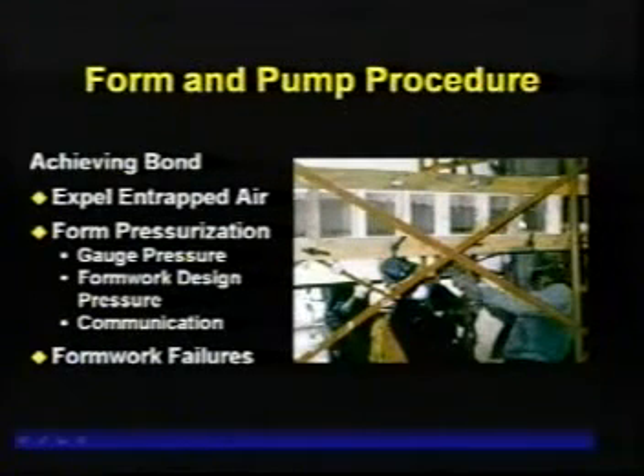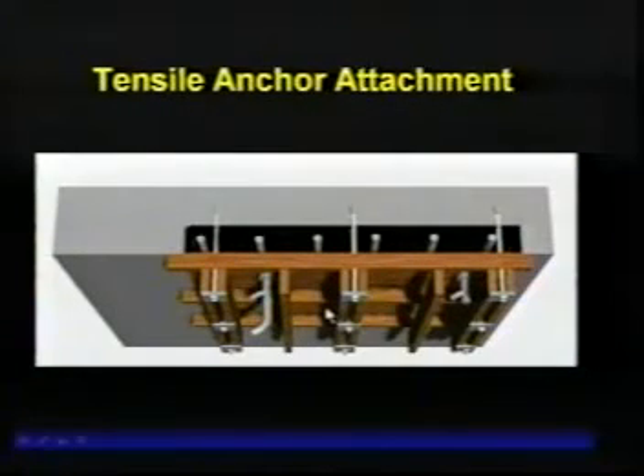And this is the last in the sequence, showing that the cavity has been filled, the form is pressurized, and there's actually some pressure gauges you can see right here, and we actually pressurize it to about 14 psi, at which point the valves are turned off. You can see how this consolidates it by just the internal pressure, how it pushes it around and consolidates, and especially the intimate contact it develops on the upper side with the existing concrete.